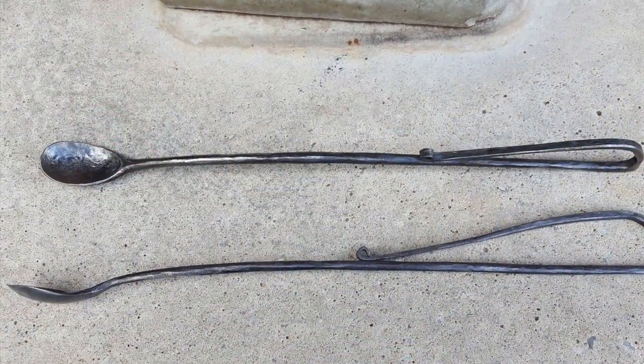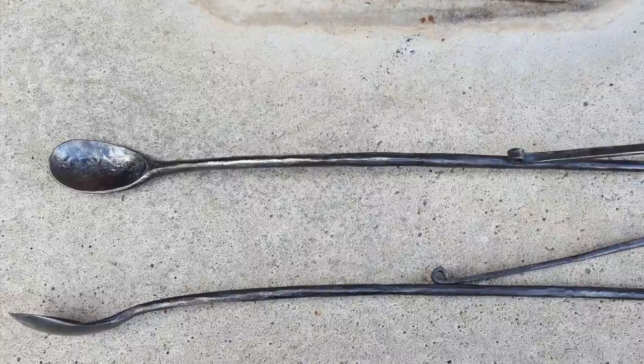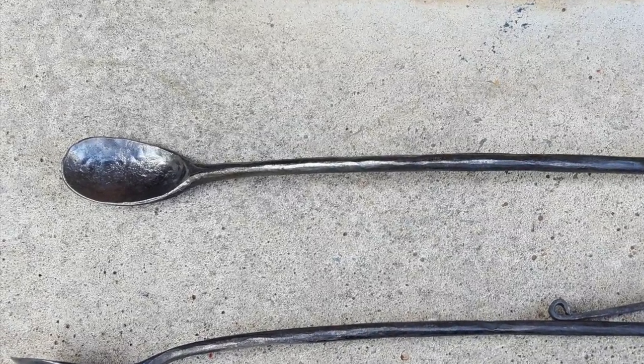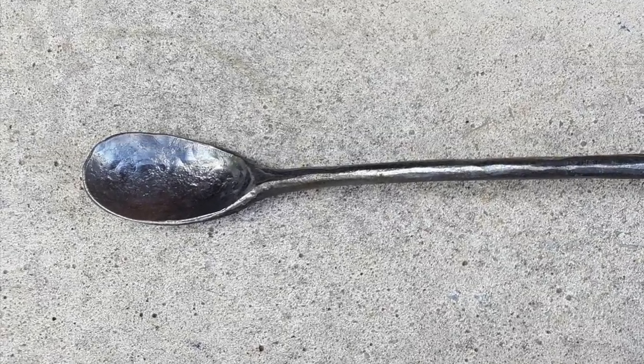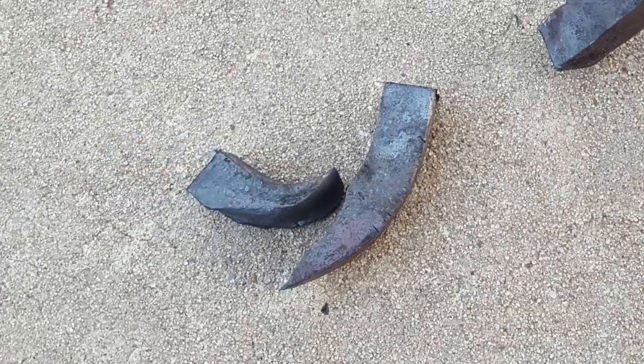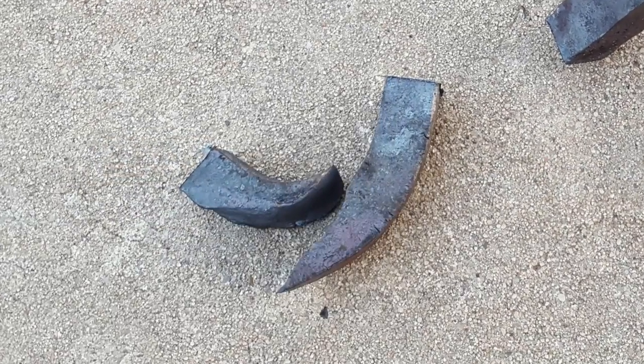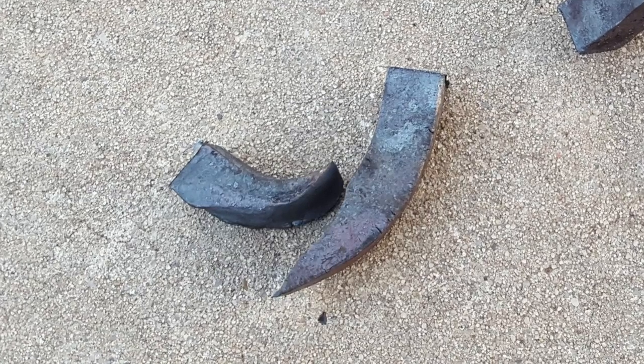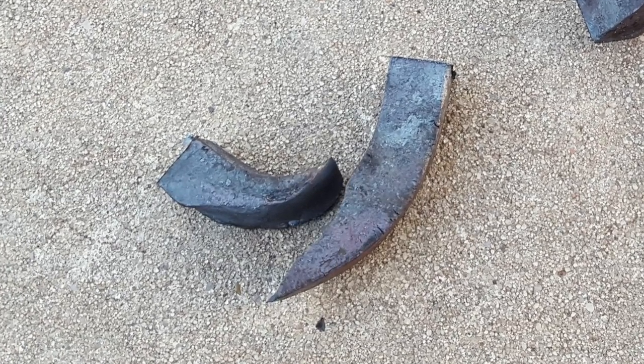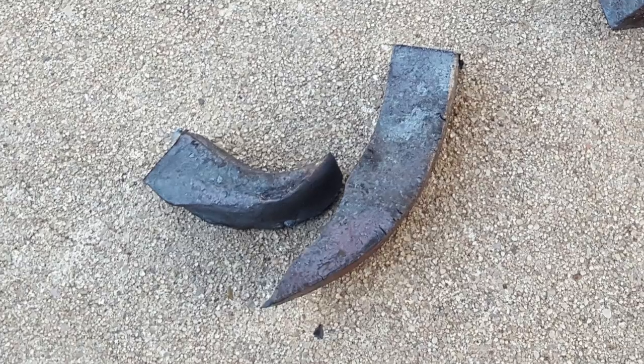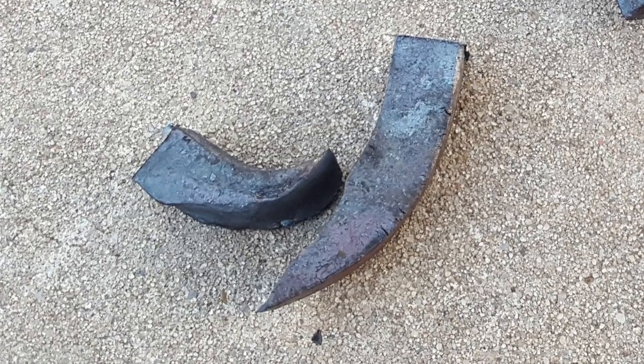My welds have proven fairly serviceable. As you can see, the faggot weld shown previously is strong enough to handle thinning into the bowl of this flux spoon. On the other hand, this lap weld was tested to destruction and it broke along the weld. It was certainly strong enough for ornamental work, but it obviously did not reach parent stock strength like a fully mature weld. I think a hotter welding heat would resolve that.